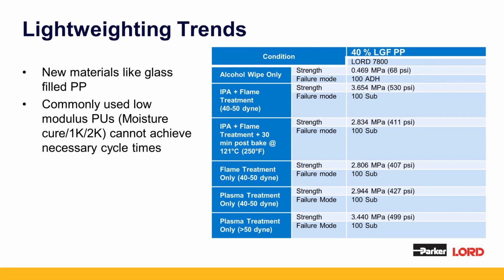Typically, manufacturers then increase the viscosity and make it much more of a viscous paste to sort of hold the parts together so they can gently be removed from the tooling. Oftentimes, however, there are quality issues associated with this. What I wanted to highlight here is the performance of the new 7800 fourth generation polyurethane on these long glass fiber polypropylene substrates. The first one, where we did just an alcohol wipe, that's a very low surface energy.